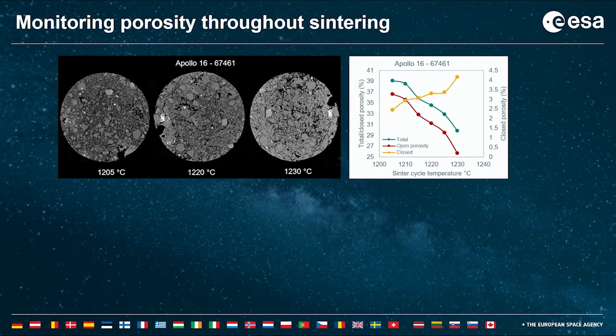So to look at monitoring the porosity throughout the sintering process, we're using XCT primarily. You can see there the difference in the material structure of one of the Apollo 16 samples going from 1205 to 1230. And we can monitor the porosity as it changes throughout, and the open and closed porosity. It's quite hard to compare the materials to each other because, as I showed in the last slide, they have very different average particle size, and so the porosity is not directly comparable.